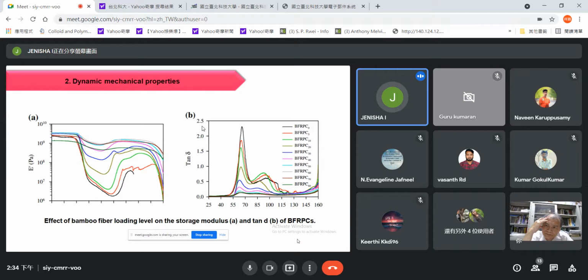This is because the drop is mainly because of the amorphous nature of the polymer, and the increase at 120 degrees Celsius is because when the polymer is exposed to temperature, it undergoes annealing and forms some crystallite structures, and thus there is some increase in the E prime at 120 degrees Celsius.